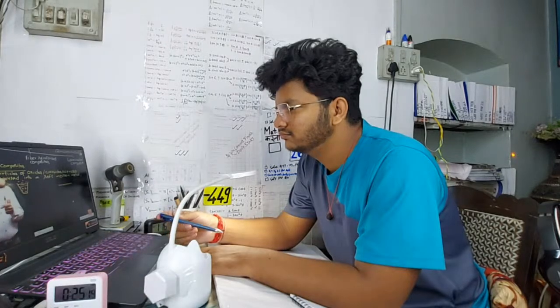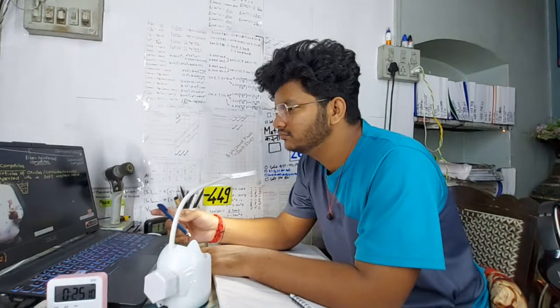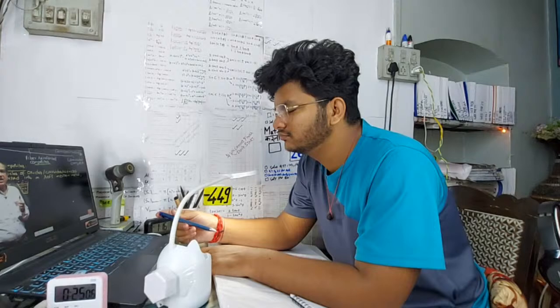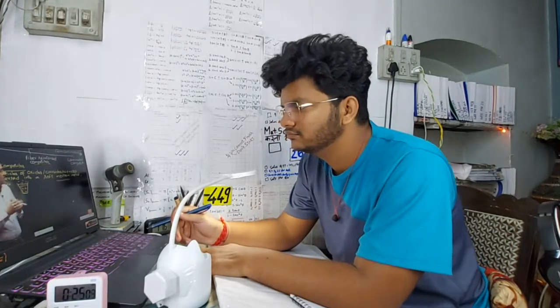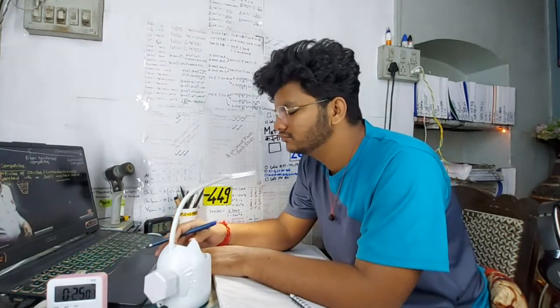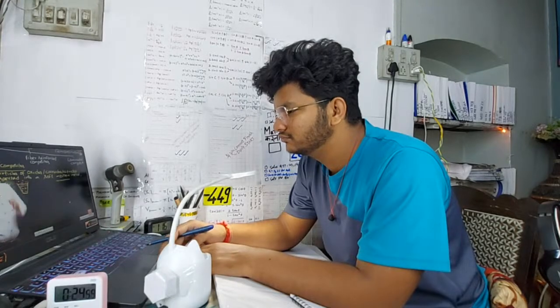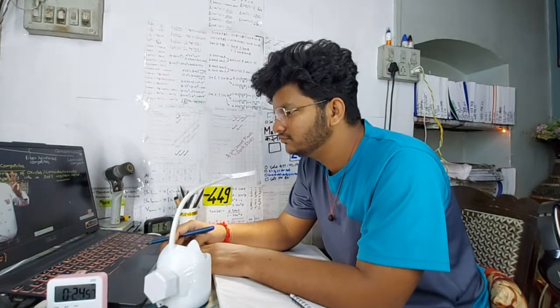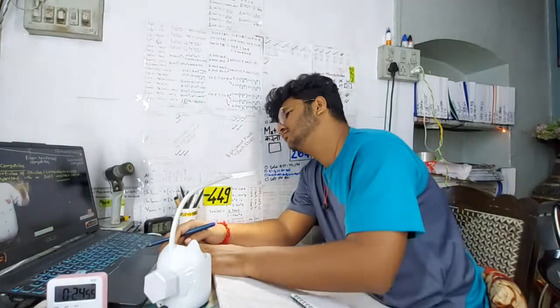Friends, in a tension test, as you keep on increasing the applied load steadily, beyond yield point, the dislocations in the base metal lattice will start. Suppose the base metal is aluminum, dislocations in the aluminum will start moving. When moving dislocations come across the hard carbide or oxide particles, dislocation movement is going to be stopped. When dislocation movement is stopped, slip will be arrested. Resistance to permanent deformation is increased. That is the reason why strength will increase, hardness will increase.